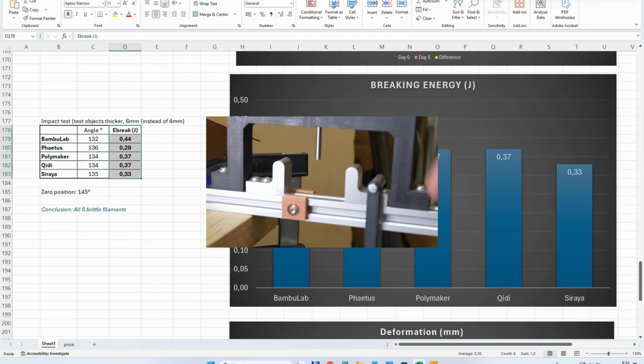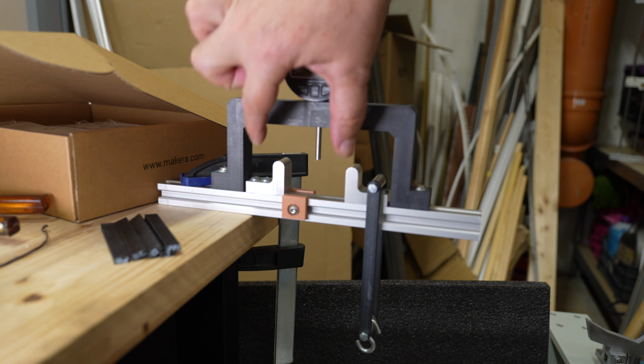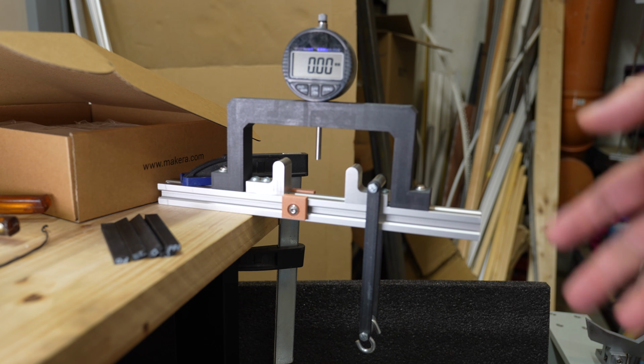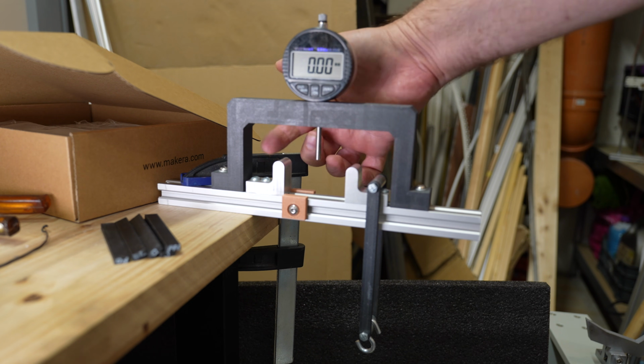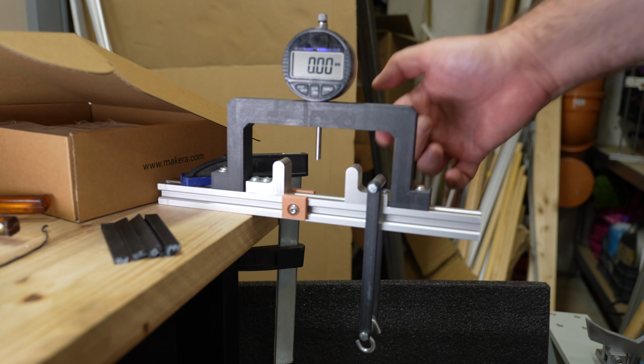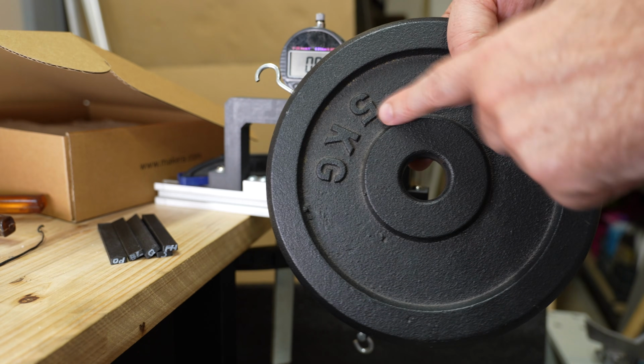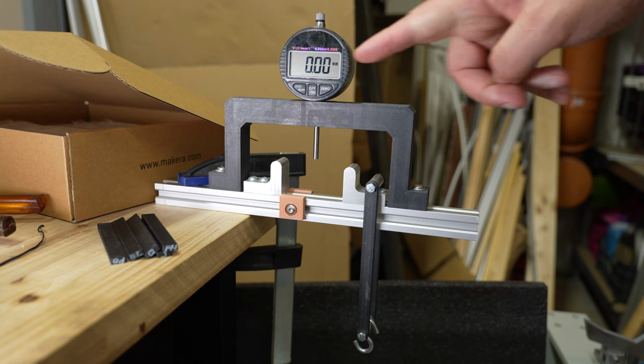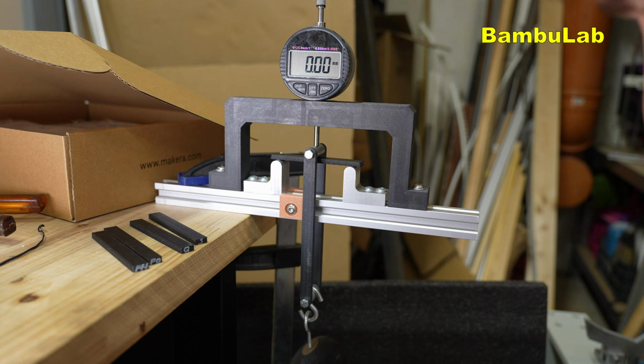carbon fibers. 3-point bending test, and the distance between supports is 64 mm, which follows the ISO standard better. Also these supports are rounded, the diameter is 10 mm, and I will place a 5 kg load and I will measure the deformation after exactly 30 seconds.